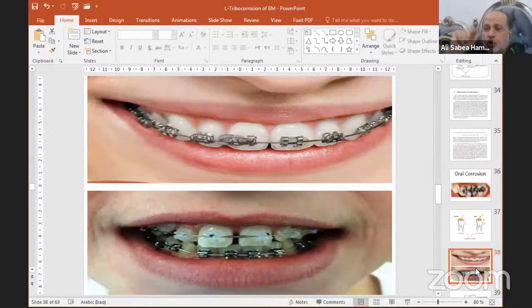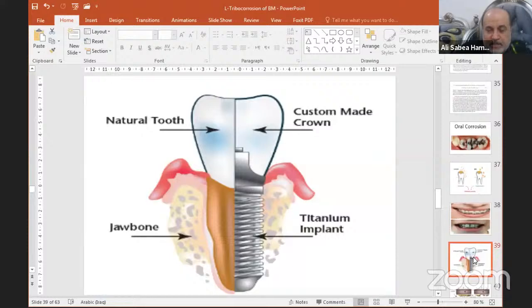And other research about 2101. My PhD student worked on 2101, improving the surface by ion implantation and by plasma spray coating at the surface of duplex stainless steel, by nitriding and by titanium nitride. 2101: 21 chromium, 1 nickel. Another example is corrosion of dental implant, titanium implant, jawbone, natural tooth, and this dental implant can be subjected to tribocorrosion.